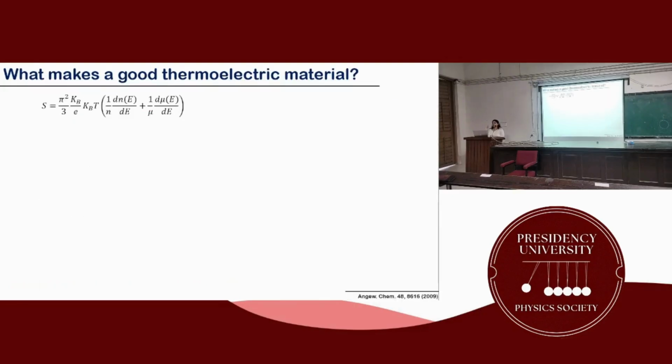So first, for that, as I say, we need to know what makes a good thermoelectric material. We need a high S. But what other things influence getting a high S? So we know this Mott equation, where this part, this N and sigma, is coming from the fact that it is ∂/∂E of log sigma, which is basically how much electrical conductivity is changing when you're changing energy.